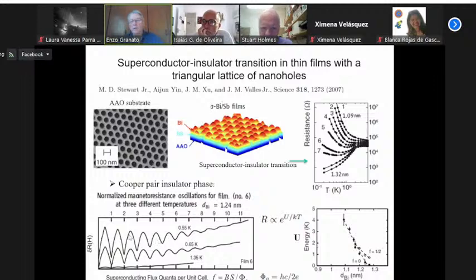But the other oscillation that you have, like a fractional oscillation, you need to go beyond this, because there is a commensurability effect. These vortices do not fit in the pinning center. So this major oscillation at the zero field can simply be explained in terms of what we call the Little-Parks oscillation. Yes, in the past, it is basically this effect.